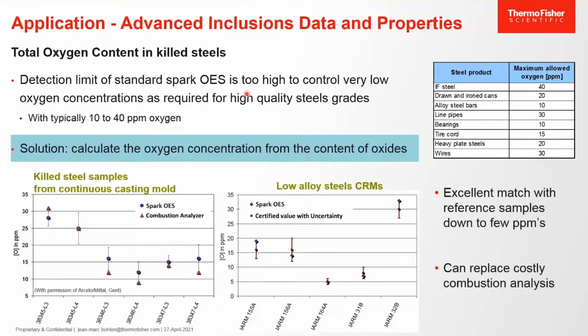The solution is given by the inclusion analysis, and we calculate the oxygen concentration from the content of oxide. Here you have an example of killed steel samples from a continuous casting mold that were measured with a combustion analyzer and with the Spark OES. You can see all the samples are below 30 ppm oxygen, so normally not possible to analyze by optical emission. But with the inclusion analysis, we are able to obtain a good match of the concentration obtained with the combustion analysis down to very low amounts of oxygen.